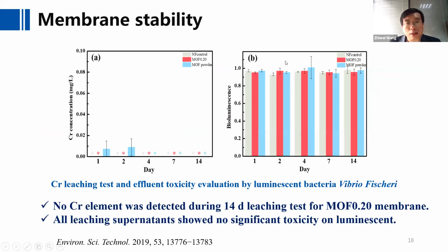Also, you will care about the membrane stability of the MOF modified nanofiltration membranes. So we carried out the soaking and leaching test for 14 days. And we found that no chromium element was detected during the 14-day leaching test for the MOF modified membrane.